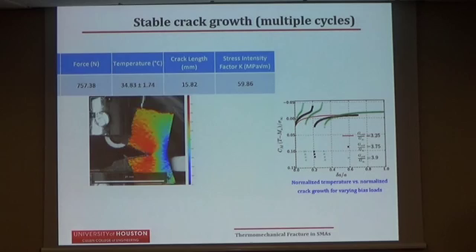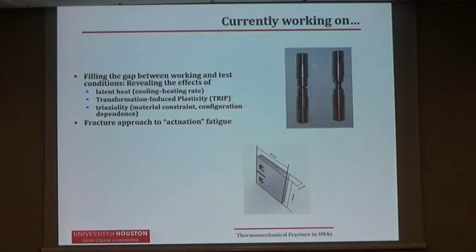So what we are trying now to do is to understand the effects of the cooling and heating rate, transformation-induced plasticity, and the triaxiality effects, because we are talking here about extended phase transformation that goes all the way to the boundary and starts interacting with the boundary conditions, so it is a large-scale transformation condition. And we would like also to move into the fracture approach to actuation fatigue.